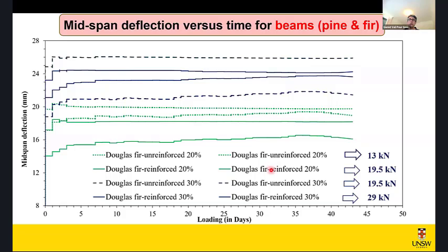So we applied higher load on the reinforced alternative. But if you compare this one, the dashed line or the dotted line, with the solid line, you clearly see the reinforced alternative subjected to even higher loads has less deflection, around 17 millimeter versus 19 to 20 millimeter for the unreinforced one. We applied again a higher level of loads on similar beams, and we came up to 30%. And you see now for the unreinforced beam, it's 19.5. For the reinforced alternative, it goes to 29 kilonewton.